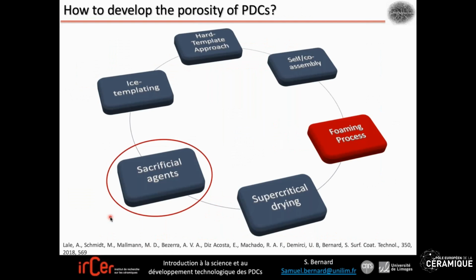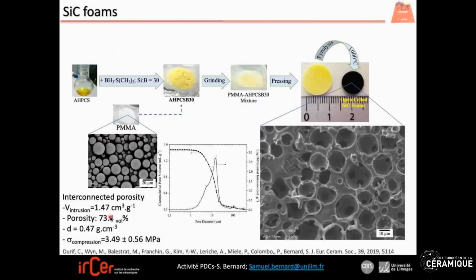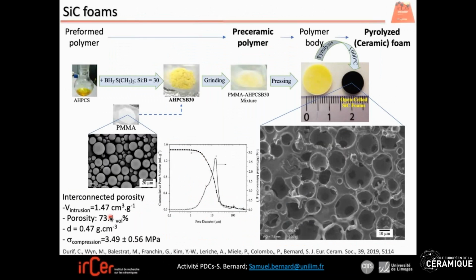So second example, a last example to design the porosity of PDCs, the use of sacrificial agents. So again, you can recognize the different steps of the PDC strategy. You start with a preformed polymer commercially available, a silicon carbide precursor, for example, polycarbosilane. It is modified with a low molecular weight compound to add other elements, boron here. Then it is mixed at microscale with PMMA spheres as sacrificial agent. So you form your precursor, which is a mixture between your preformed polymer modified at a molecular scale and PMMA. You can control the ratio between both compounds.